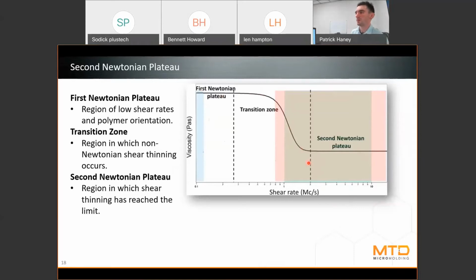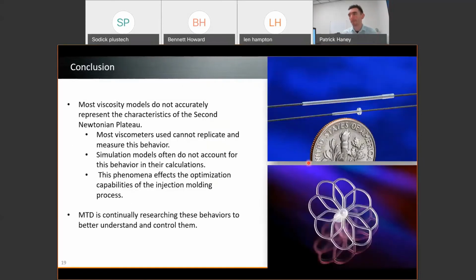Okay, so we end up with vastly different predictability in simulation or theoretical viscosity models versus what you end up seeing in real life. And this ends up being really important because it affects the way that we optimize, or that you have to think about your processing parameters. Like if you were to use the viscosity and shear rate curve to find an optimized velocity, right? But that theoretical equation no longer represents how the shear thinning behavior is actually behaving in the real world, then you have to become very creative at determining how you're going to optimize or determine your processing parameters, right?